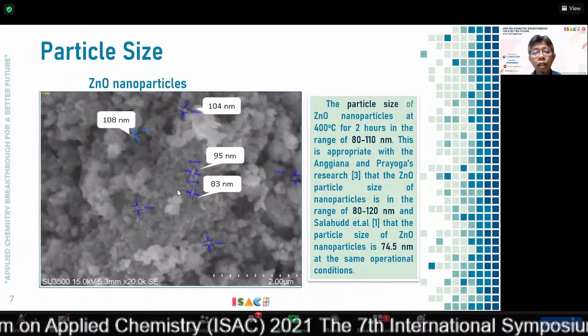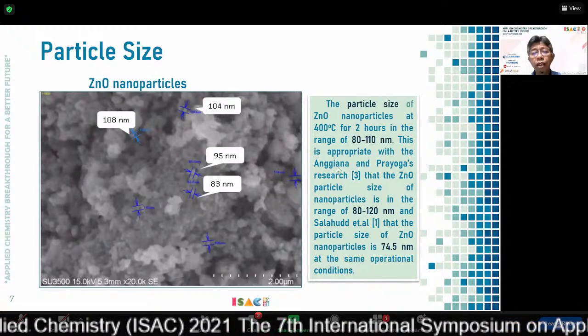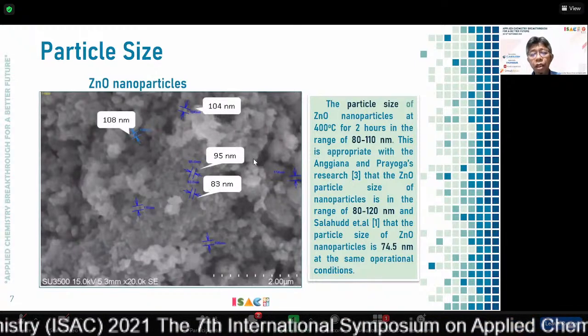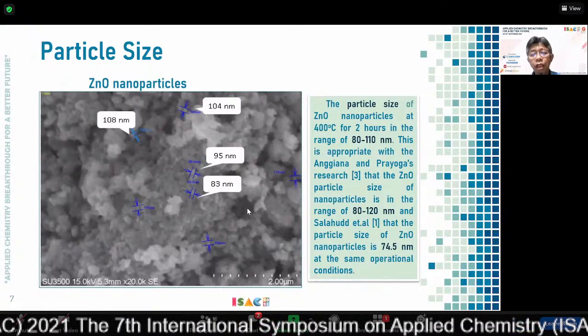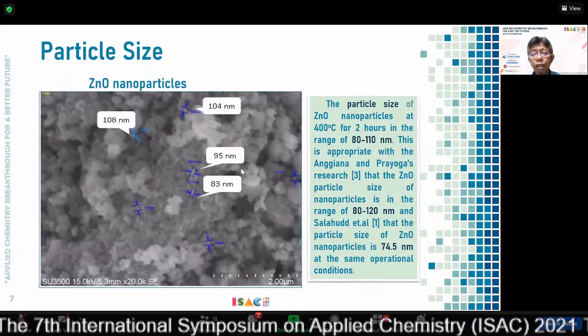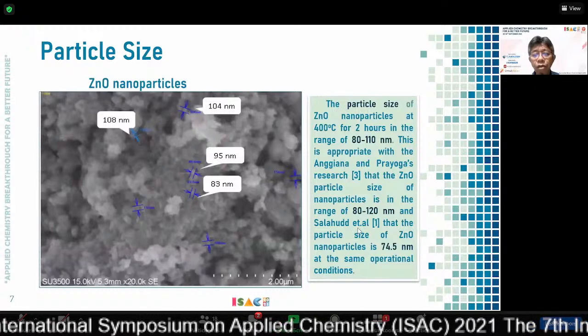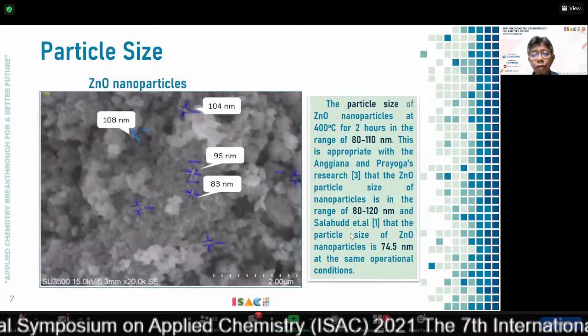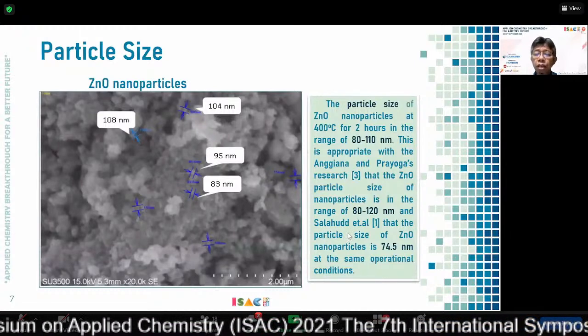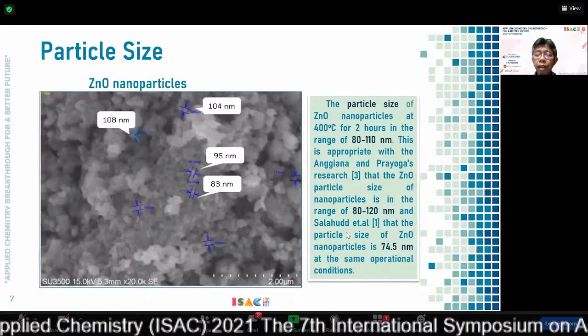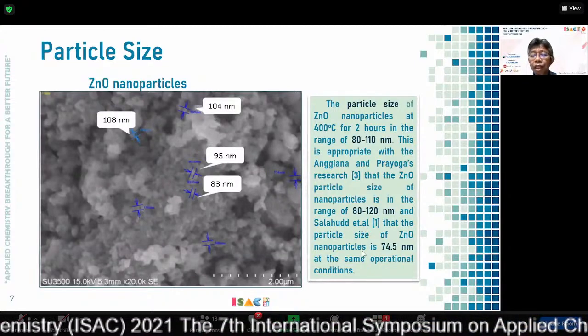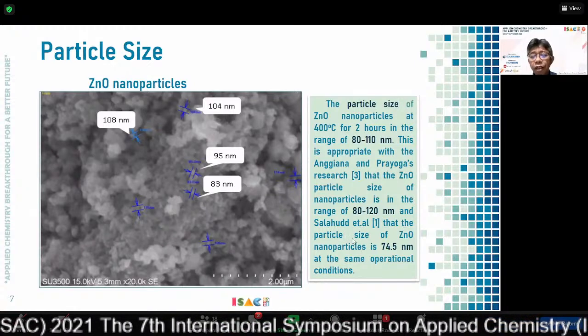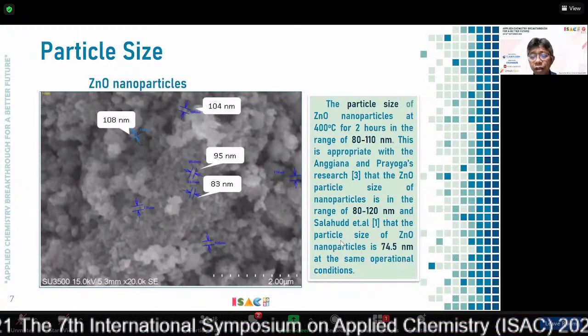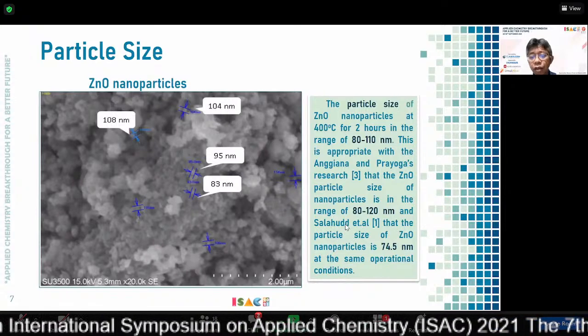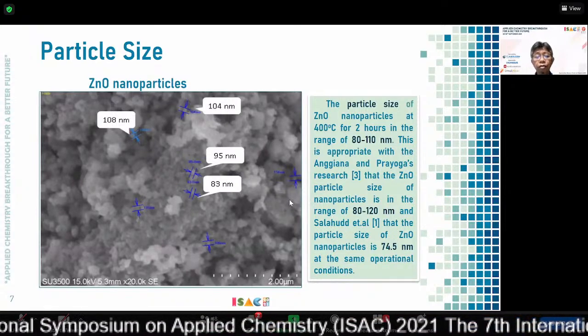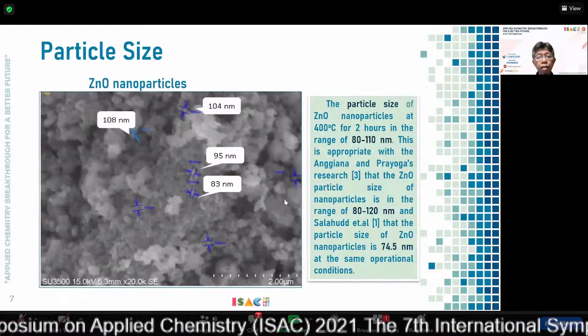And this is also consistent with the finding by Anggiana and Prayoga that the particle size is between 80 up to 120 nanometers. And Salahud also observed, using zinc chloride and the precipitation method as well, with the calcination temperature at 400 degrees centigrade, that the particle size is about 74.5 nanometers.